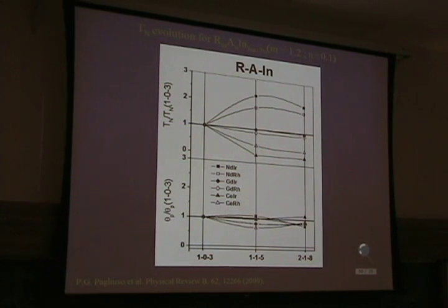When you go to low temperature, you start to depopulate the states. Look at what happens. When you look at neodymium, you see that you have an enhancement of the Néel temperature for the tetragonal compounds, and you have a suppression of the Néel temperature for the cerium compounds, right? And for gadolinium, nothing is happening. So what's the main difference between gadolinium, cerium, and neodymium?